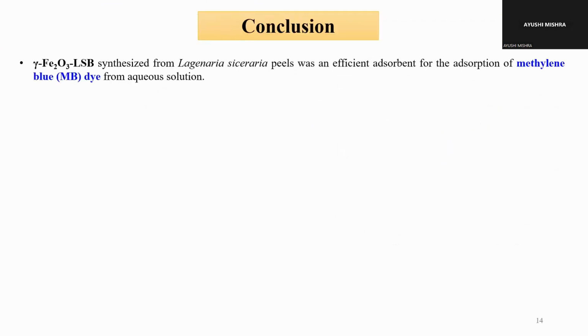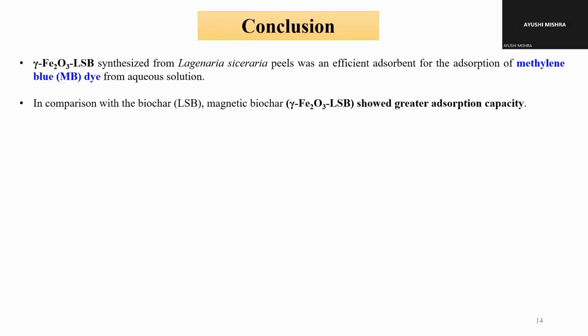After this, these are the conclusions of my study: we have synthesized a magnetic biochar that comes out to be an efficient adsorbent for the adsorption of methylene blue dye. In comparison to biochar, magnetic biochar showed greater adsorption capacity, which I told earlier, is clearly due to the extra functional groups on the surface.